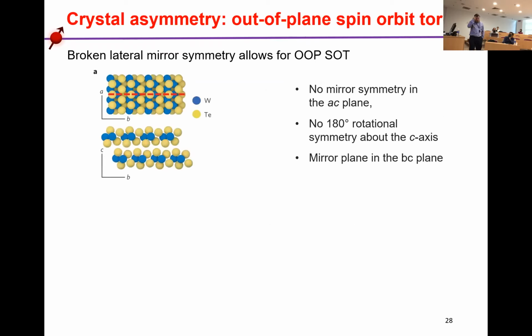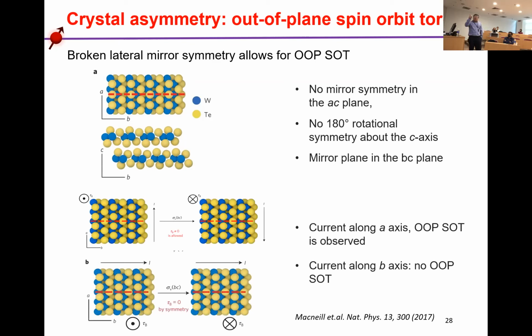Actually, this was first proposed by Professor Ralph's group at Cornell University, but they used the tungsten ditelluride material. This material has no mirror symmetry in the AC plane, but there is a mirror plane in the BC plane. So he demonstrated by using ST-FMR. When the current is perpendicular to the mirror plane, there is an out-of-plane spin torque. This out-of-plane spin torque can in principle switch the perpendicular magnetization. And when the current is parallel to the mirror plane, no out-of-plane torque can be generated. But they only demonstrated that this out-of-plane torque exists, but they did not demonstrate the field-free switching